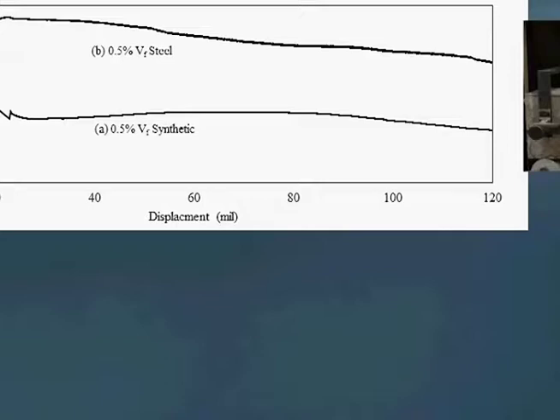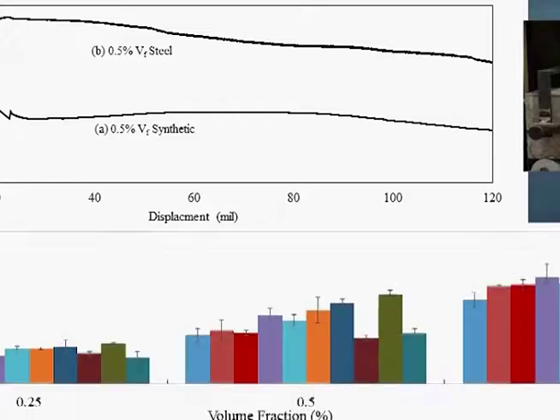But actually we do not use them because probably they are heavy, and there are construction issues. Moreover, if we use synthetic fibers, the required performance is probably good enough. Synthetic fibers can serve our need. So this is the contribution, not the modulus of rupture or compressive strength. You see here we can increase the residual strength.